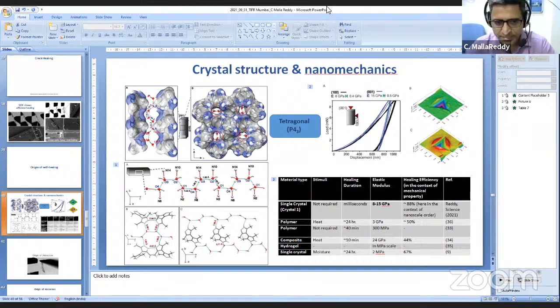Okay. See, we have not thought about this enough actually. We see some correlation. If you have a crystal which is plate-like, depending on which side you break it from, we see some difference. But again, this is a little complex. Suppose you have a flat, plate-like crystal, and you land the crystal on the flat surface, and then push it from the side. The crystal is nicely on a flat surface, right? So you also have enough surface in the same direction.